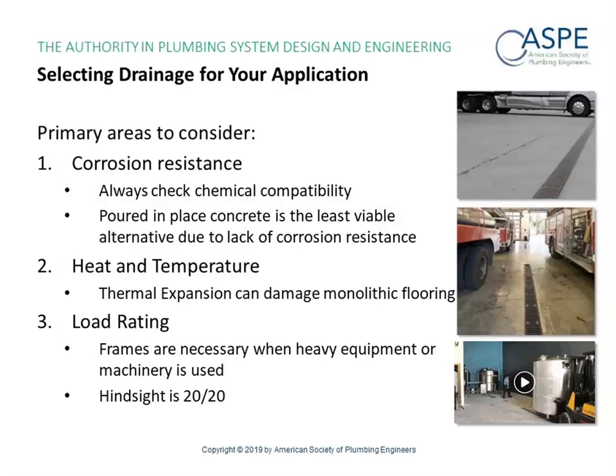If you're using a plastic, an iron, a steel, just do your due diligence and make sure that you do get that chemical list from the client, which I know can be a daunting task in some cases, but I would advise it. I can tell you that poured-in-place concrete is absolutely the least viable alternative due to lack of corrosion resistance. You can epoxy line those. However, I was just in a facility 2 weeks ago where they had done just that, and that epoxy had peeled off, so that concrete then acts as a sponge.